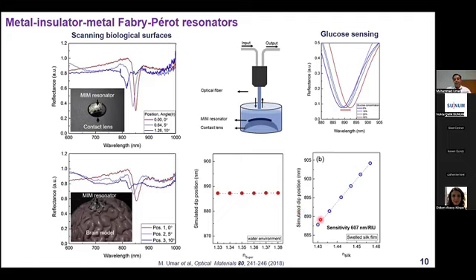Also, we checked if we change the refractive index of the silk in the water, which means we are adding more glucose, the resonance is shifting from 887 to 905 nanometers. So the refractive index sensitivity is 607 nanometers per refractive index unit. So the refractive index sensitivity of this device is also very high.